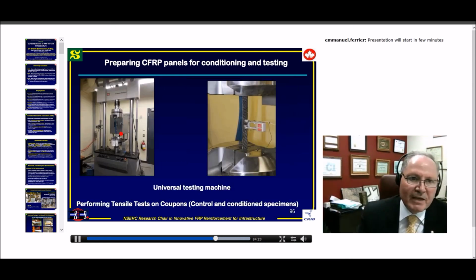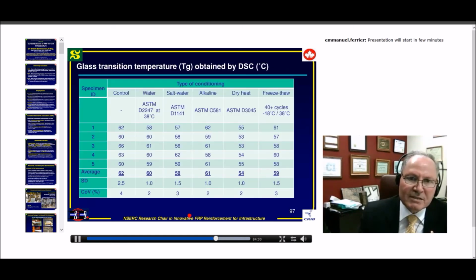So you can see here the MTS machine that we used for testing the control and the conditioned specimens. And this is also what we did about glass transition temperature by DSC, because when we complete the conditioning, we also have a limit on the temperature. It has to be, I think, 50 Celsius. And as you can see here, the control 62 and water 60, 58, 61, 54.